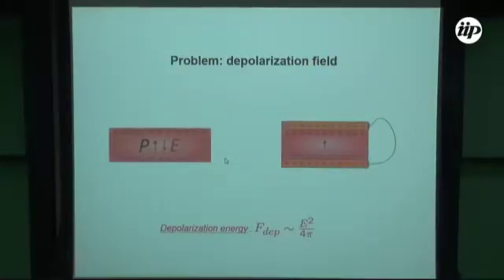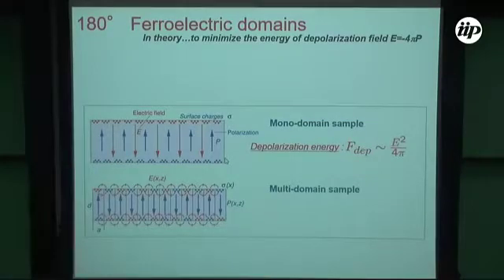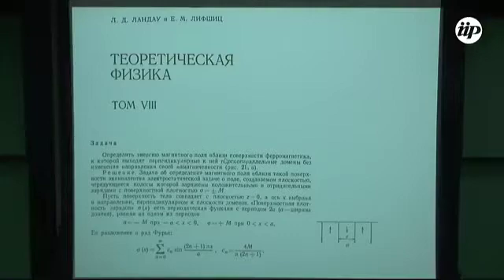So what is the problem? Actually, the problem was the problem of Batra and Silverman. The problem is that there are these depolarization fields. So the depolarization energy is huge, and in principle, it should kill ferroelectricity. In macroscopic samples, usually all the experiments were done either with electrodes, or with some charged ions that were coming from the air, and they screen the depolarization field. But when we are coming to the nanoscale, one can show that because of the finite screening length lambda, the screening will become less efficient.